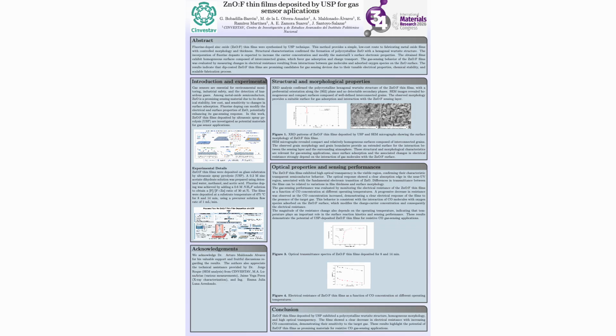Now, looking at the structural and morphological characterization, the X-ray diffraction results confirm the formation of polycrystalline ZnO with a hexagonal wurtzite structure, with preferential orientation along the 002 plane. Importantly, no detectable secondary phases were observed. The SEM images show a relatively homogeneous and compact surface formed by interconnected grains. This morphology is particularly relevant for sensing application because the grain surface and grain boundaries provide sites where gas molecules can interact with the sensing material.